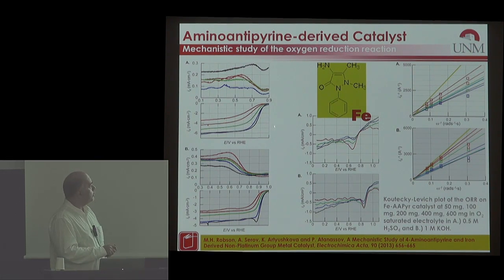Only if you learn how to make 100 micrograms, or better 50 micrograms, loadings on 1 square centimeter of rotating disk electrode, then you can see that from a transfer number of 4 electrons, with a decrease of that loading, you will go to a transfer number of 2 electrons. That is the only thing that shows you that when you put a little bit of the catalyst, the peroxide that you form doesn't escape from the matrix. And that is clear evidence for some of these catalysts of the so-called 2+2 mechanism.